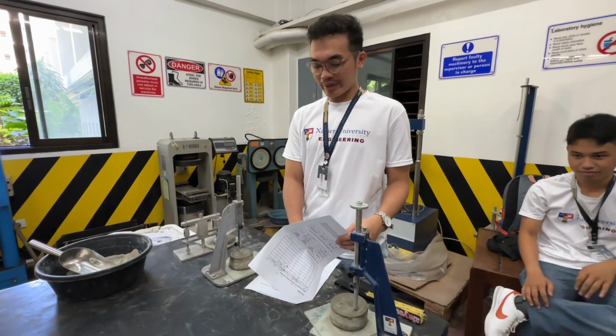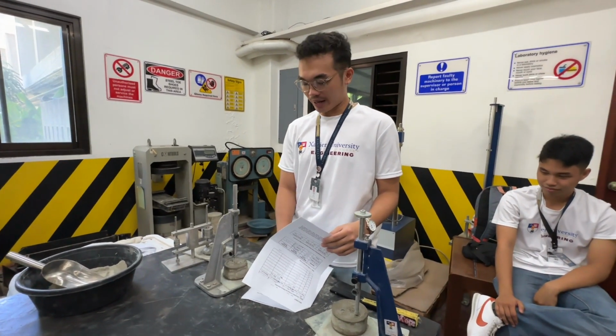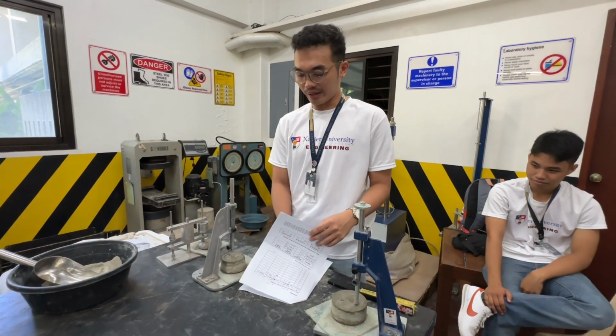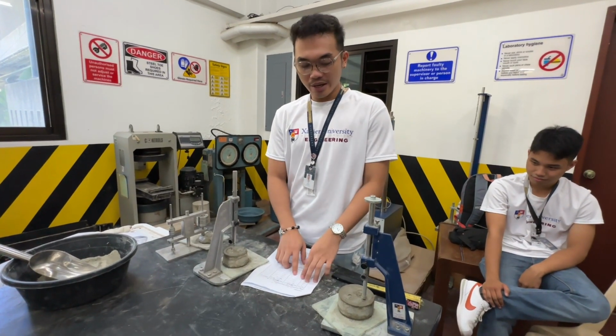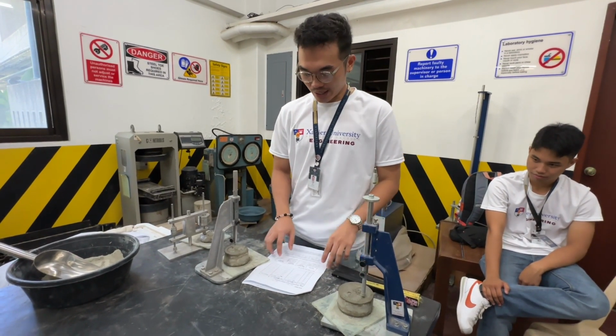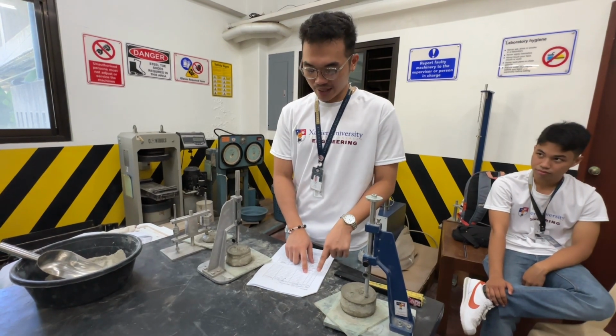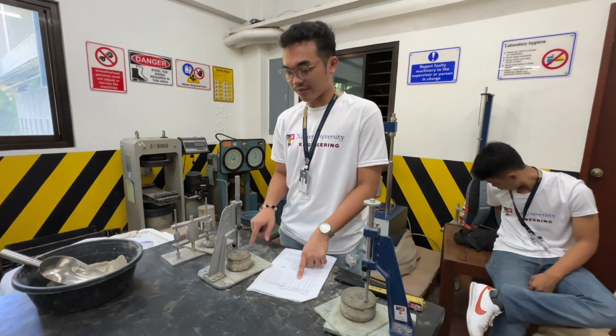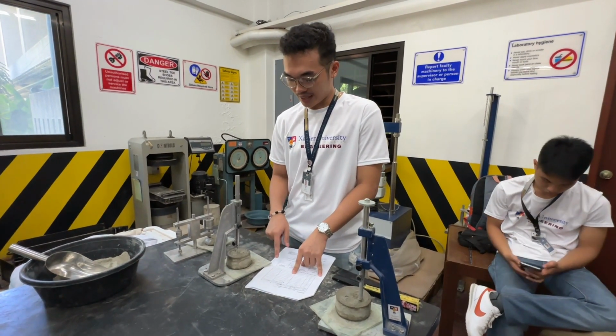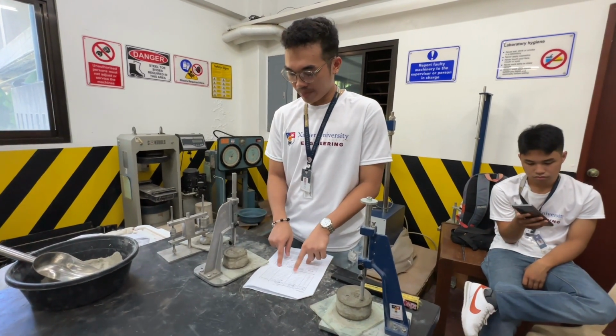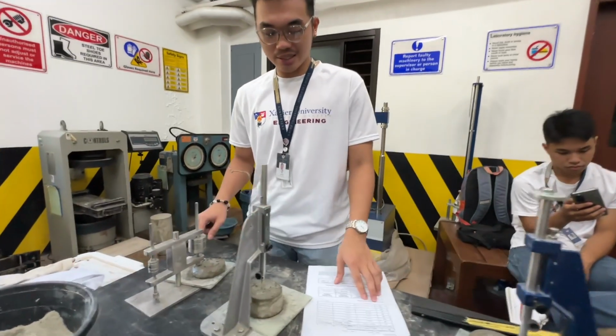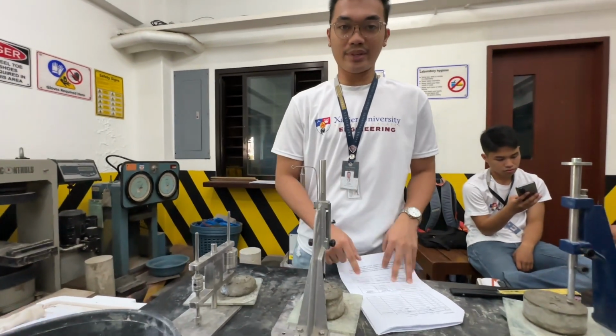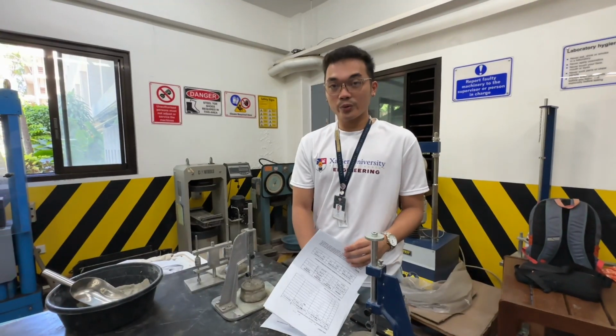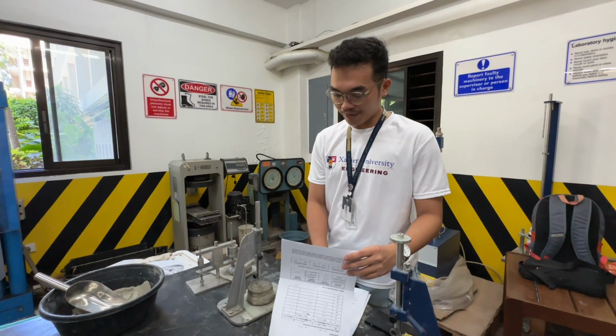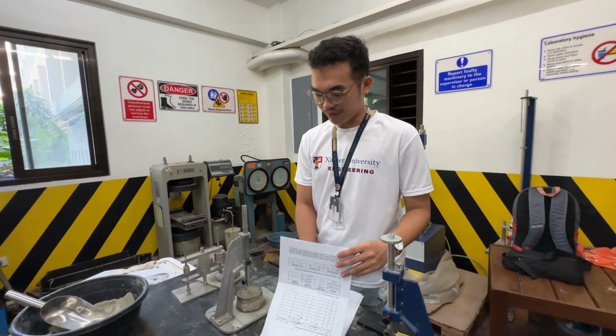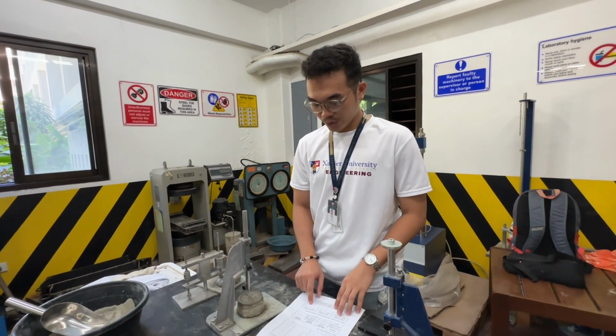Now we are done determining the time of setting of the hydraulic cement by Vicat needle apparatus and the Gilmore apparatus. So for the Vicat thick needle, its time of setting is 90 minutes, and for the Vicat thin needle, its time of setting is 120 minutes. For the Gilmore apparatus, its time of setting is 150 minutes. After that, we are now going to determine the initial and final setting time of the hydraulic cement through calculations.